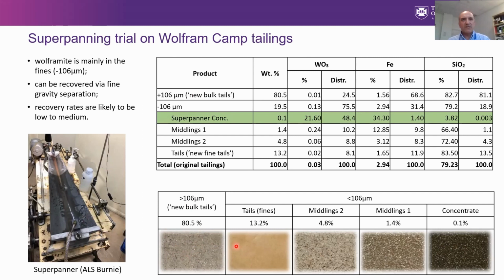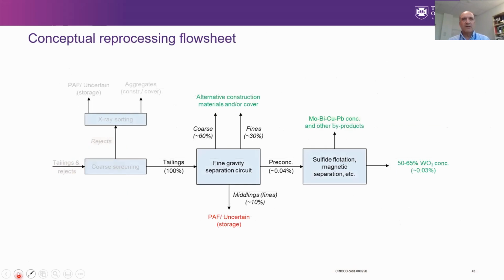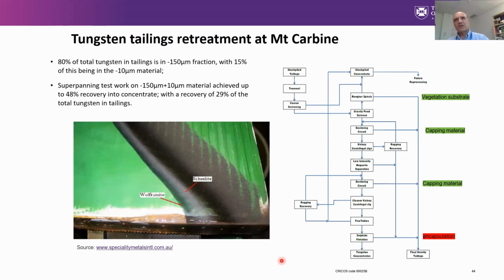which can be used as capping material for cover. We have fine, benign clay material that can be used as a sealing layer, and then we have a concentrate which has tungsten in it. And so that's a very simple flow sheet that we can use: gravity separation followed by flotation. This is a process that is happening at Mount Carbine, and they're getting some good results.